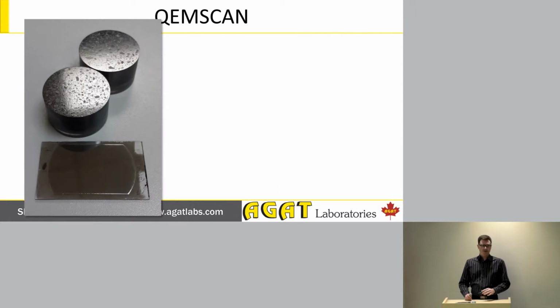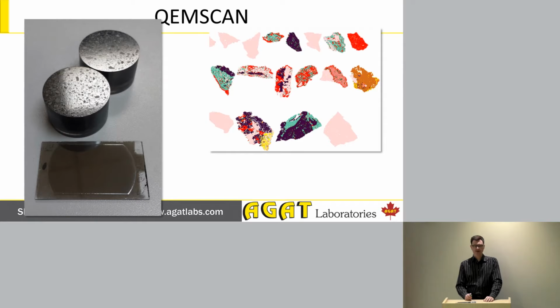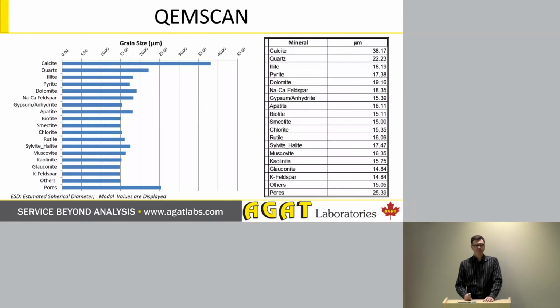In this example, we're looking at the two different modes of operation of QEMSCAN. We have two of these epoxy pucks. They're 30 millimeters in diameter, and then below that, a polished thin section. From the pucks, we obtain little maps of each individual grain within a puck, and from the polished section, we get a map over a region that is selected within that section. We can also do this at various resolutions, and we can zoom in on features of interest, for instance, this interesting replacement texture, to see what's going on in more detail.